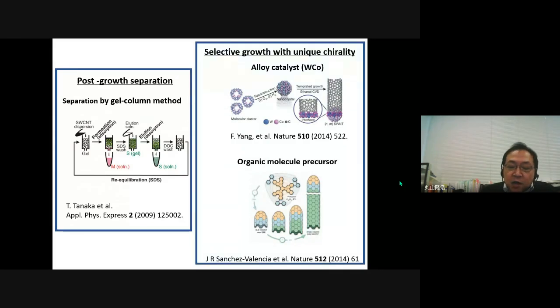Peking University group attained selective growth of single-wall carbon nanotubes with unique chirality by using alloy catalysts, tungsten cobalt. And the German group reported selective growth by using organic molecule precursors. However, the obtained chirality is limited, or the yield was not high. So, selective growth of single-wall carbon nanotubes with unique chirality is still an important issue.